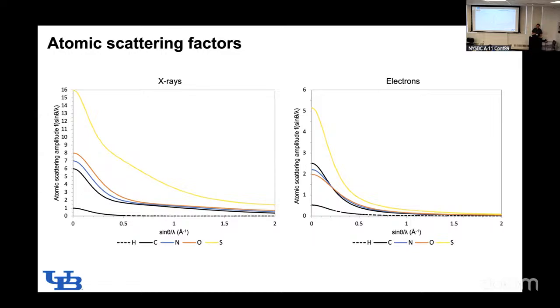In electrons, this is not the case. If you look at the scattering factors for carbon, nitrogen, oxygen, they actually kind of jump up and down. This has to do with an unsolved physical problem called the mean inner potential. This tracks back to the idea that electrons scatter from the Coulomb potential of the crystal rather than the electron density. It's just different physics telling you different information.